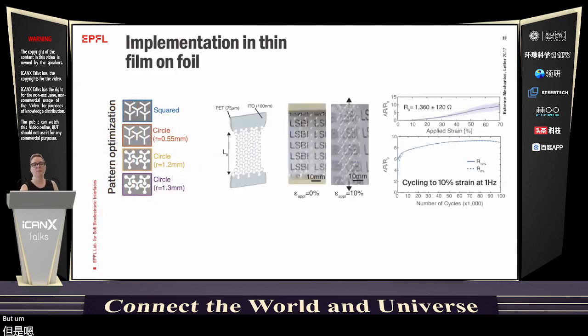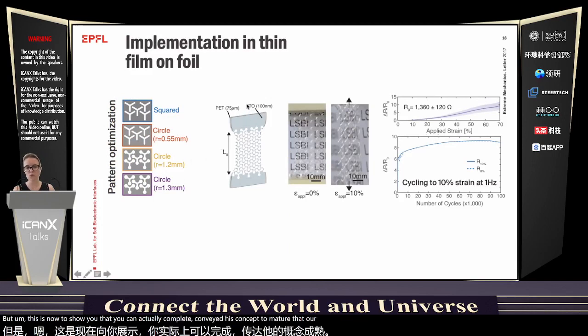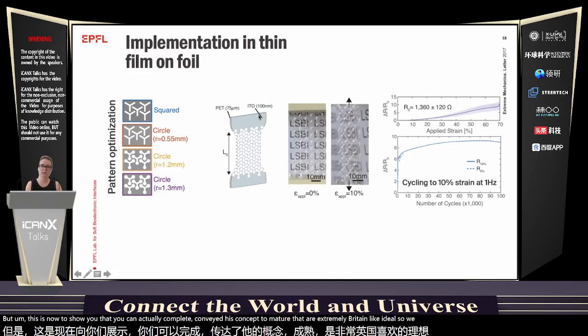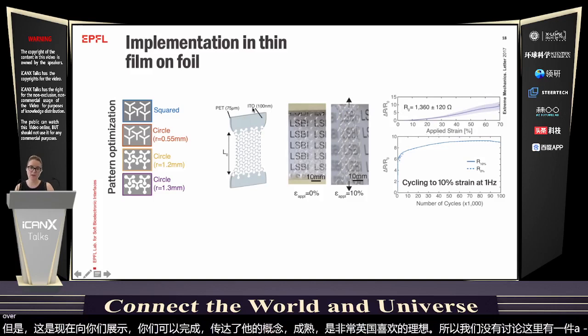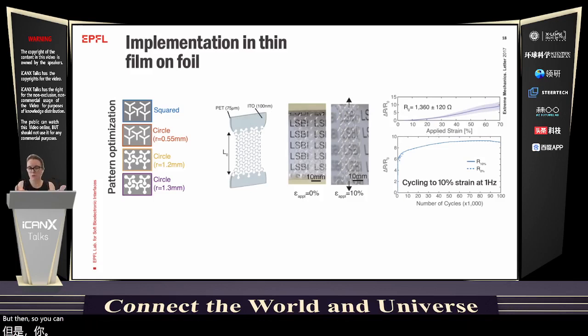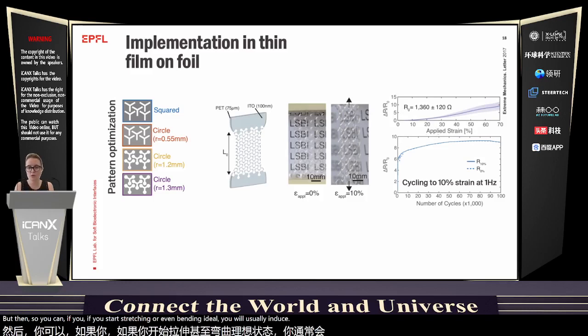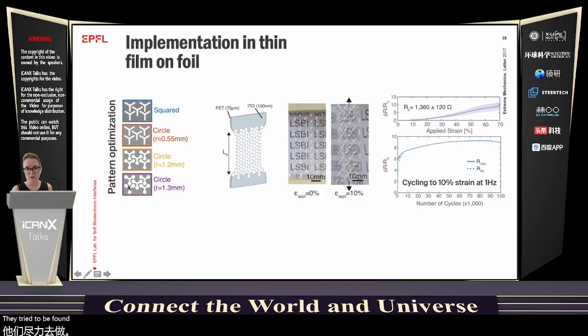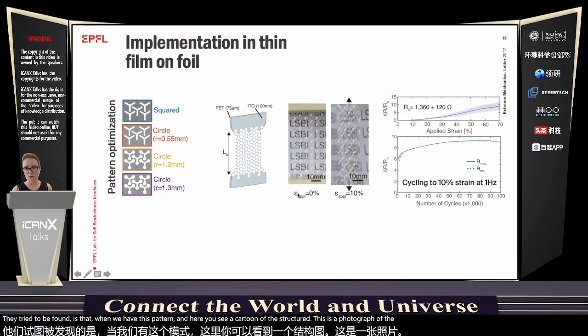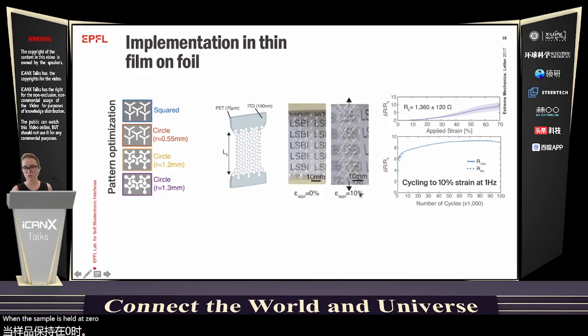But this is now to show you that you can actually convey this concept to materials that are extremely brittle, like ITO. So we did this test where here we have a PET sheet, which is also a thermoplastic, onto which we deposit a thin layer of indium tin oxide, which is a very brittle material. If you start stretching or even bending ITO, you would usually induce catastrophic cracking. But what we found is that when we have this pattern, and here you see a cartoon of the structure, this is a photograph of the pattern when the sample is held at zero strain or 10% strain.